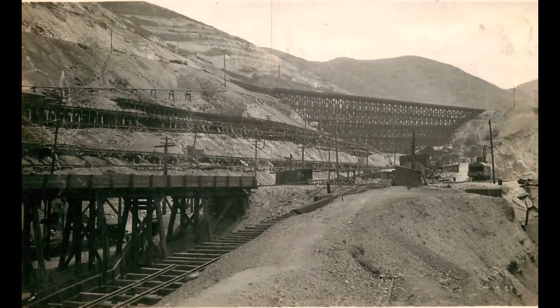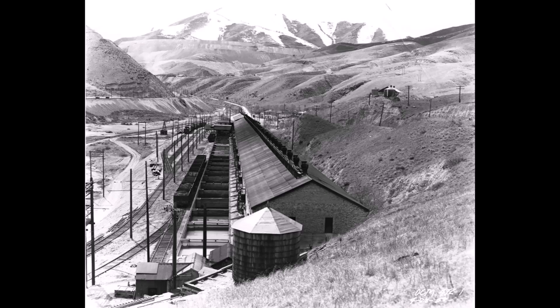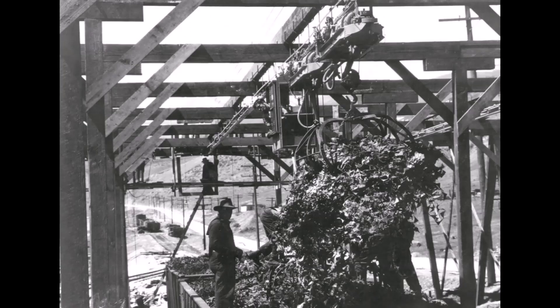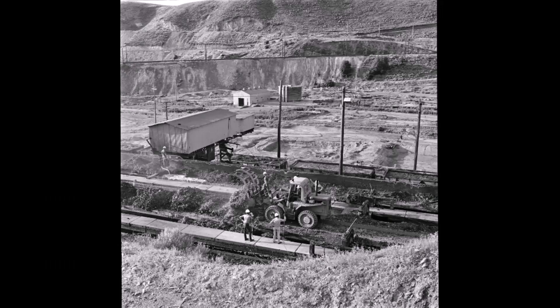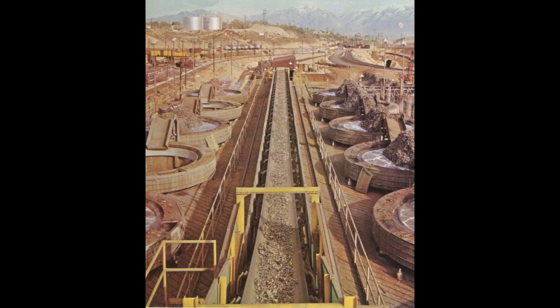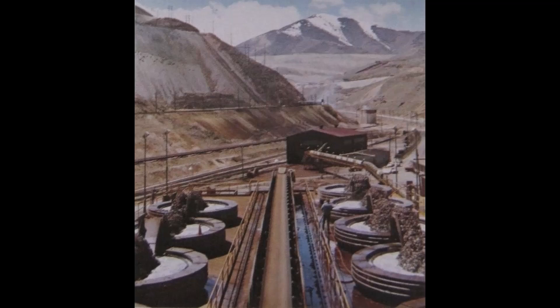The leaching process was not new. Old miners would place barrels or tubs — sometimes called launderers — near the mine dumps and add scrap metal. The chemistry was simple: the green water is high in sulfuric acid, and the chemical reaction consumes the steel and removes the copper ions from the water. Then it settles to the bottom, becoming 75 to 90 percent copper.